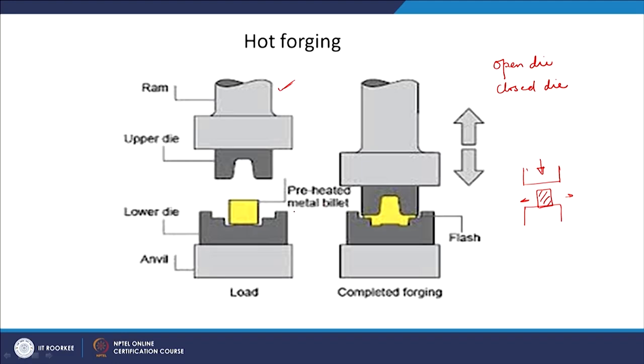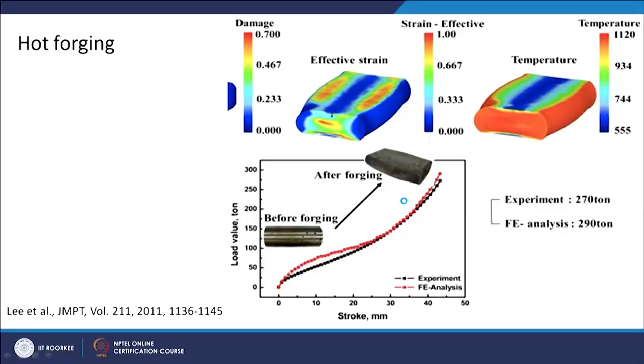So a preheated metal billet will be kept, and then you will hammer with the upper ram, and the material will be kept on the lower ram. It can be done in a repeated cycle, so it won't be a one shot process, you keep hammering till the material takes the shape of the die. Again, people have done studies, some experimental, some FEM simulations, just to show what kind of strain rate and temperature you can attain in the material.